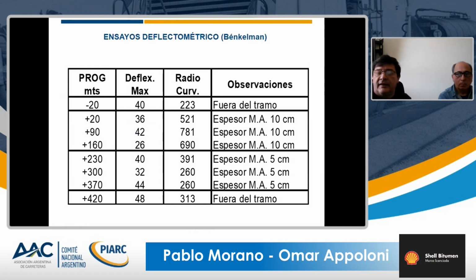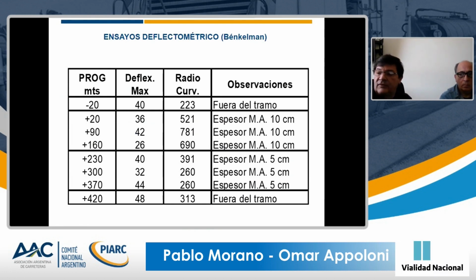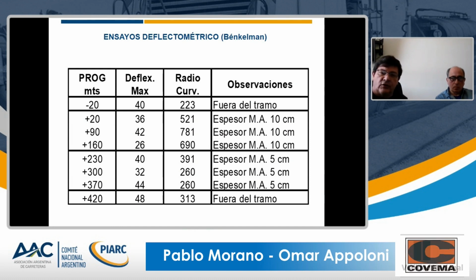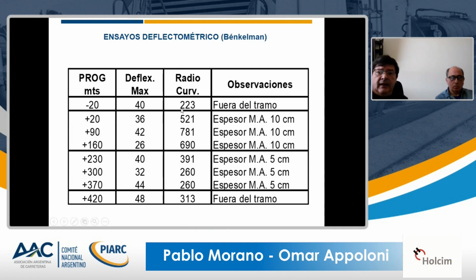Another important thing that was done was that at that point we did not have a deflector, and we used a Benkelman for deflections in the two areas with different thickness, and in the other one that was outside the test area.